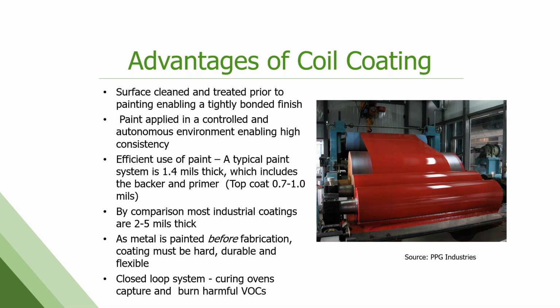the amount of paint. And because all of this is done before the fabrication of the final part, these coatings have to be hard, durable, but yet flexible as well. So there's a lot of chemistry and science that goes into the paint to make this happen. The coil coating process, while we're using solvent-based paints, is a closed loop system. Our curing ovens capture and burn all the VOCs. We're not releasing anything into the environment, which is nice.